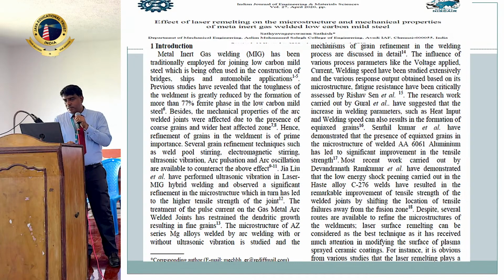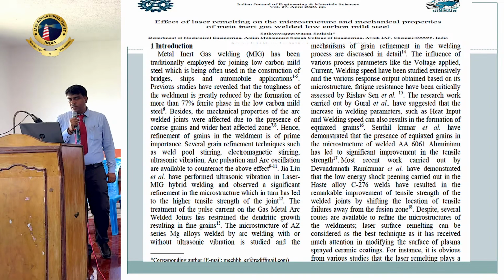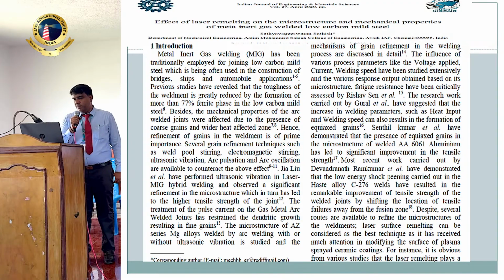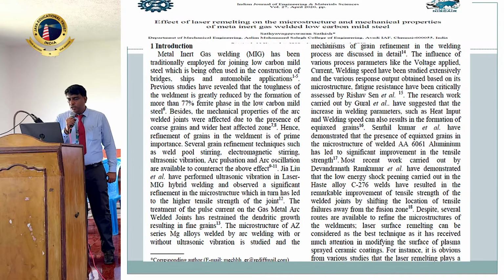The second paragraph, that is Senthil Kumar et al. have demonstrated that the presence of equiaxed grain in the microstructure of welded AA6061 aluminum has led to a significant improvement in the tensile strength. Most recent work carried out by Devendranath Ramkumar et al. have demonstrated that the low energy shot peening carried out in the Hastelloy alloy welds have resulted in a remarkable improvement of tensile strength of the welded joint by shifting the location of tensile failures away from the fusion zone.